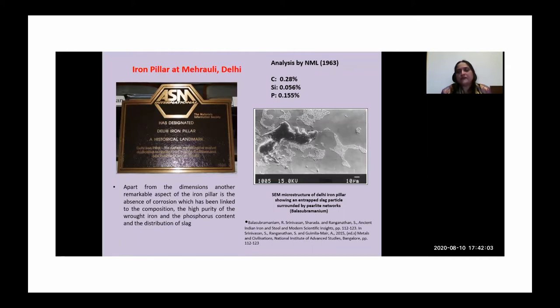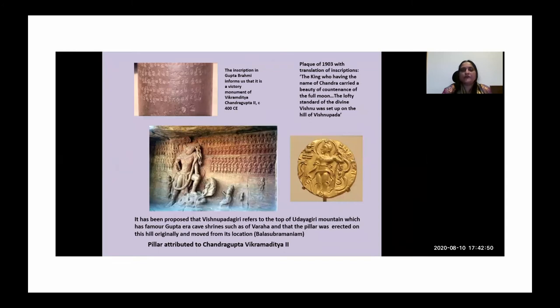And you can see here the scanning electron microstructure of the section of the Delhi Iron Pillar, which shows that it has entrapped slag particles, which are surrounded by pearlite networks. And so this slag is also considered to be a factor in enhancing the corrosion resistance, because it's been hammered and forged so well that the slag has been quite uniformly distributed, and that also tends to contribute to the corrosion resistance. And of course, the relative humidity of Delhi is also very low, which has also helped. You see that the top part of the pillar is in pretty good shape compared to the bottom part of it.